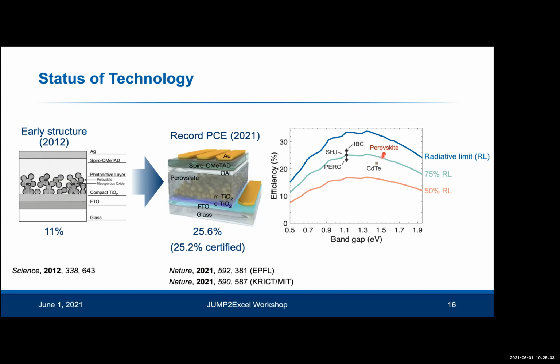And if you map that out onto this chart here, comparing with the radiative limit, what you can see is that already, even though the perovskites are a much younger technology, they have surpassed the best efficiencies of cadmium telluride. And they've gone past the 75% of the radiative limit line, and they're at the cusp of matching the best efficiency for crystalline silicon devices. And that is really quite remarkable for a solution-based technology made using normal lab-based equipment rather than an industrial production facility.